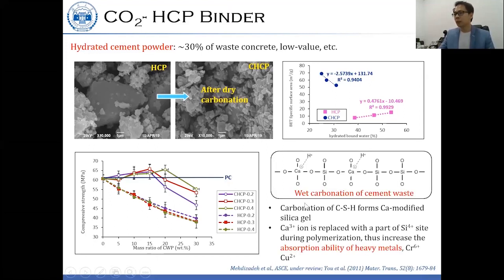In a study from a Korean research group, they used wet carbonation for cement waste. After the carbonation, the CSH was converted to a calcium-modified silica gel, in which part of the silicon site is replaced with calcium ions during polymerization. This in turn increases the capability to absorb heavy metals.